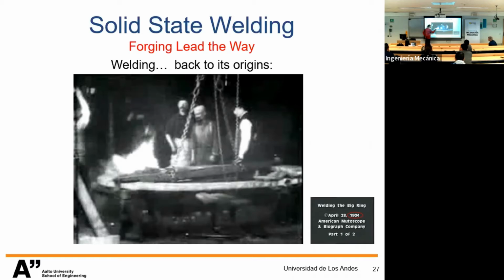And so they have to apply a heat source, bringing down the resistance of the material with the increase of temperature, the yield strength of the material that comes down with the production of heat as temperature measures the vibration and increases the distance between the particles. And when this distance increases, you can apply deformation, and with deformation, you bring the internal material to the outside, and you create this new chemical reactive state, where with mechanical activation, energetic activation, mechanical or heat, we can then process it.